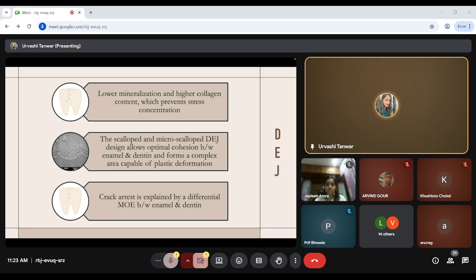So the enamel acts as a compression dome. The enamel compression loads are transferred via the DEJ to the dentine, and in this transfer, a stress concentration occurs at the DEJ as it converts the enamel vertical load into a horizontal load in the dentine. Now, these are some of the characteristics of the DEJ, which has a bit lower mineralization compared to your enamel, and it has a higher collagen content, which again prevents stress concentration. The design itself, the microscallop structure of the DEJ, allows optimal cohesion between enamel and dentine, and it forms a complex which is capable of plastic deformation, which means it is capable of some movement.